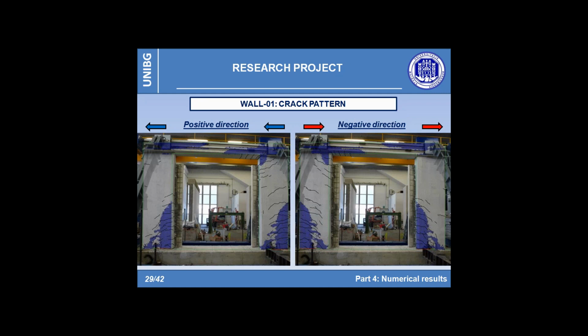As you can see, the model has proven to be reliable in reproducing the experimental behavior, also catching the inclination and evolution of the cracks. Both at the base and in correspondence of the upper beam, the crack zones caught numerically are a little underestimated, probably due to the cyclic effect that increases the damage level at each step and that here is not taken into account.